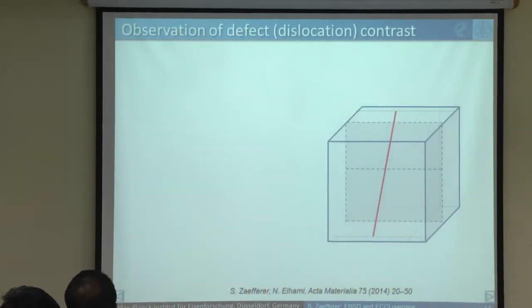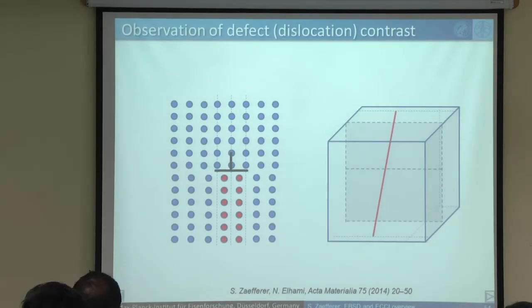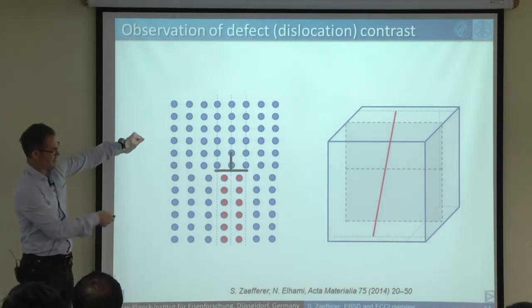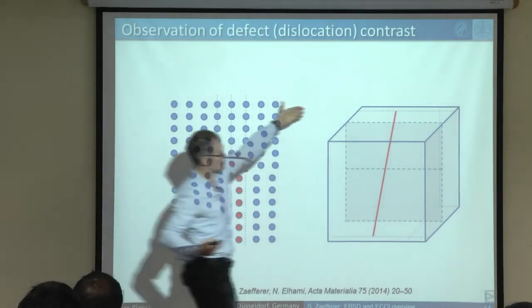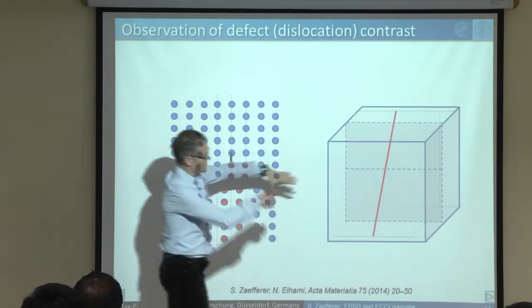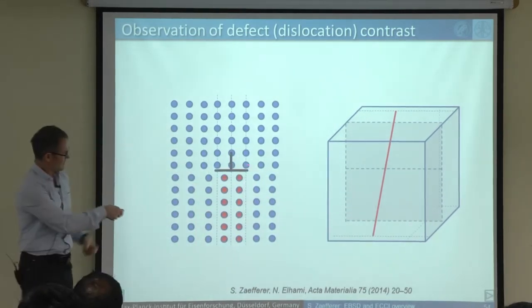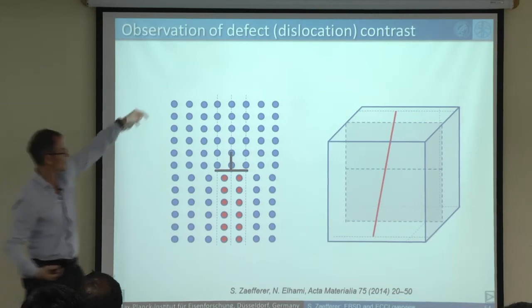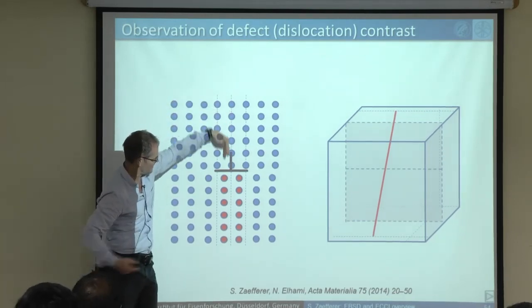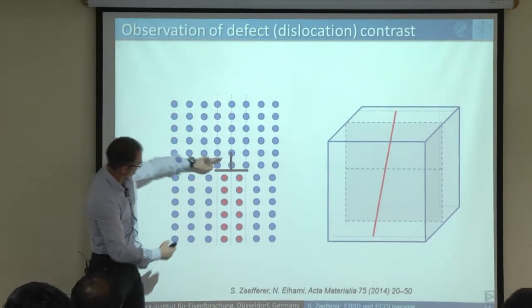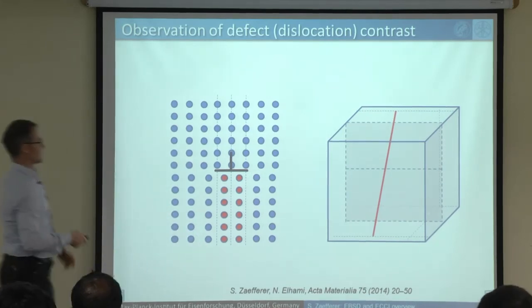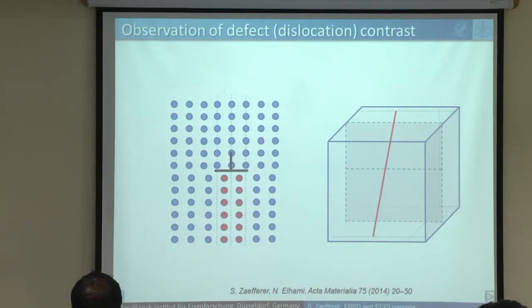Now imagine we have a defect in there. Let's say this is a block with one dislocation line inside, and this is a picture of this dislocation line, cross-sectioned somewhere in the middle of this 3D block. What is a dislocation line? It is just an additional lattice plane. So you see here below the dislocation, this lattice plane is missing, and as a result, we have here a perfect crystal, and here we have a perfect crystal, but with one plane missing.